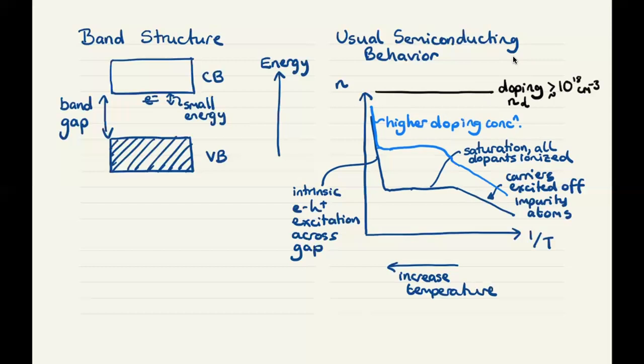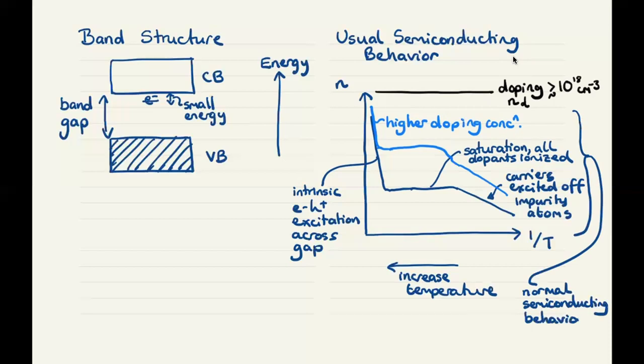So the blue curves here are all showing normal semiconducting behavior. Behavior that's exploited in semiconductor devices. And the black curve here is the degenerate regime. And in this degenerate regime, the wave functions of the electrons on the doping atoms have started to overlap and make a band.